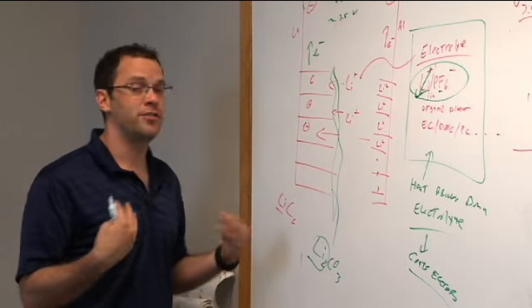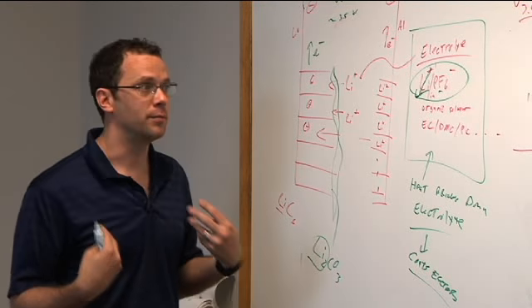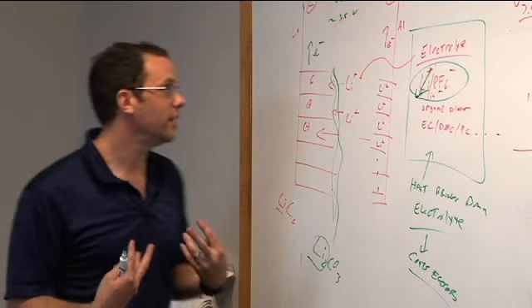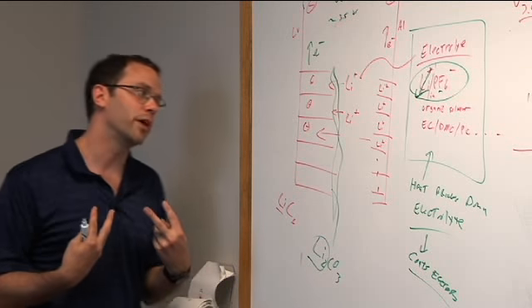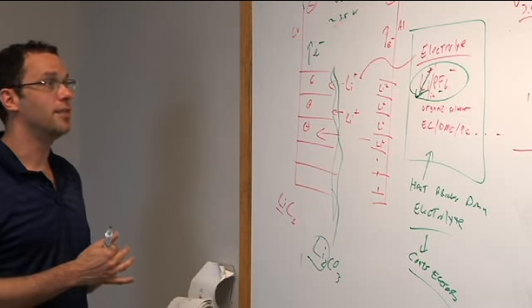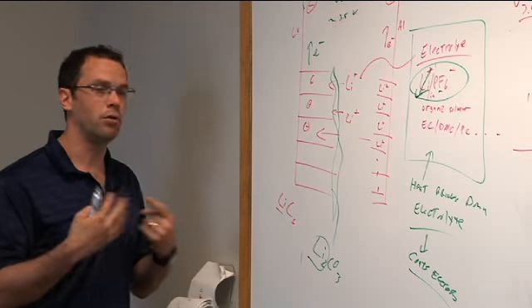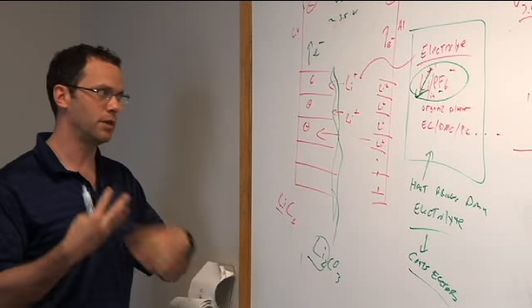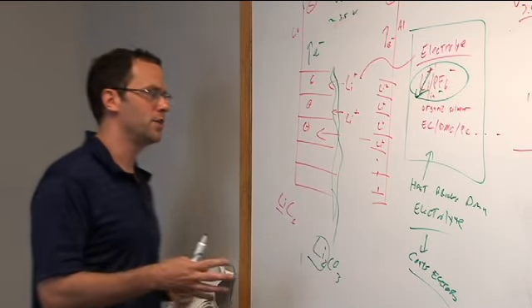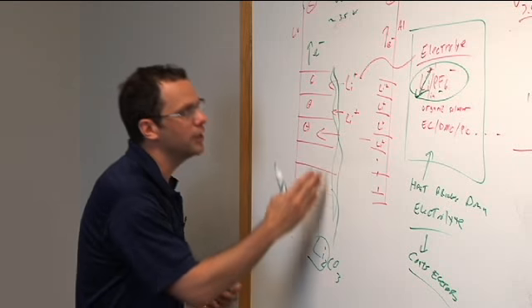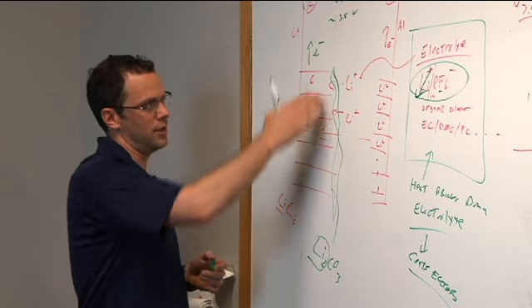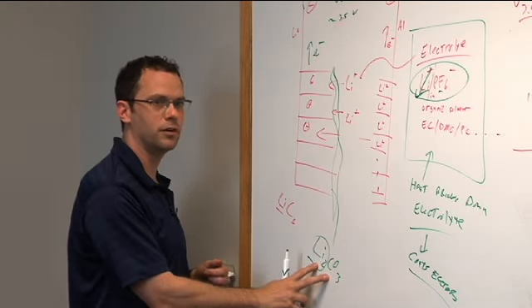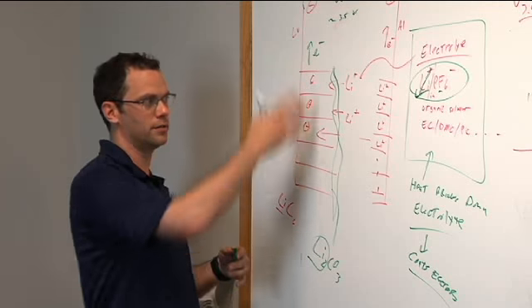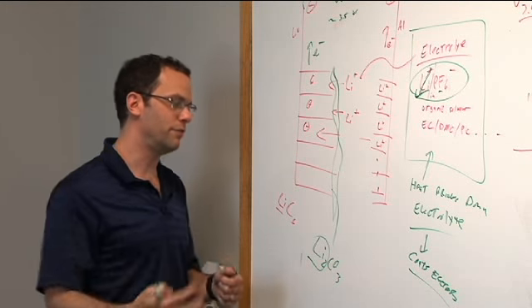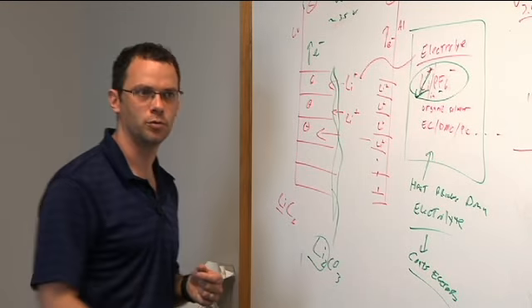And we wanted to send the cells back raw right after they made them, and they wouldn't do it. They had to take it through the formation cycling first, right? And my guess is they had some interesting pulse or some interesting different time temperature soak formation cycling that very uniformly and thinly coats the anode with a very thin layer of this stuff. You actually engineer this layer such that it's more difficult for subsequent layers to deposit onto it, right?